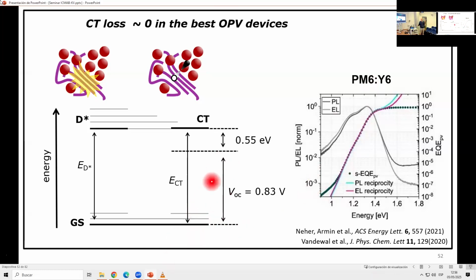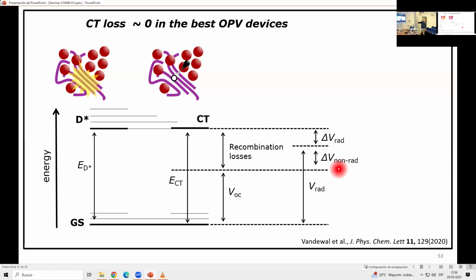So this is the highest VOC you could get by just playing with the energy levels. But we could increase VOC by reducing the loss between the CT state energy and the real VOC. Here I plot a bit. These are called recombination losses, because if you increase light intensity or you decrease recombination, this loss would be less.